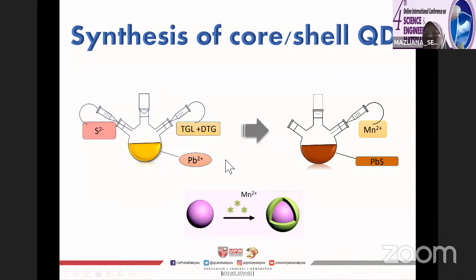The next procedure is, once we have prepared the PbS quantum dots, we mix them with the manganese precursor, and we form the core-shell quantum dots. What happens here is that the surface of my PbS quantum dots is sulfur rich. So when we introduce the manganese, there is a cation exchange between the manganese cation and the lead cation. When manganese replaces the position of the lead, we form the manganese sulfide shell layer.